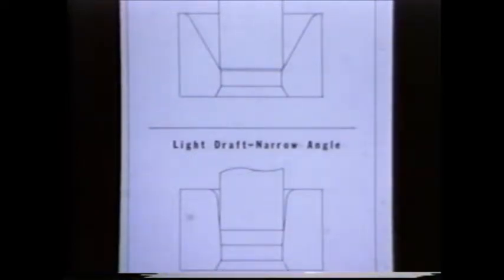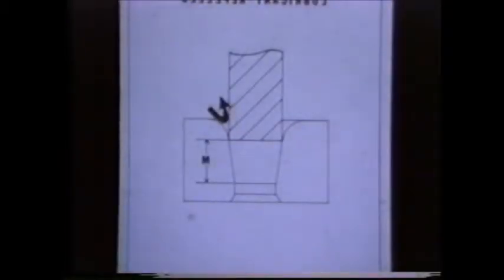We see many cases where problems are caused by the incorrect contact of the stock and the die. Light drafts are taken using approach angles which allow the entering steel to contact the die too close to the bearing, as seen on the top view. This reduces the stock too quickly. When taking light drafts, angles should be altered to accommodate proper drafting, as in the bottom view. Drafts take place too far up the die, which can actually repel the lubricant, and where the contact is outside the drawing angle, pickup occurs immediately. This is a common occurrence when using oversized hot roll.